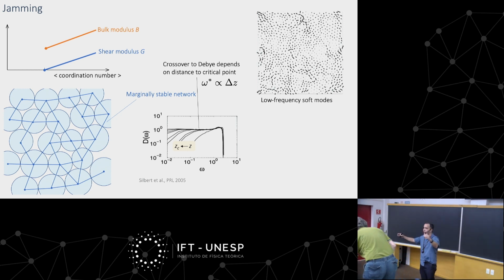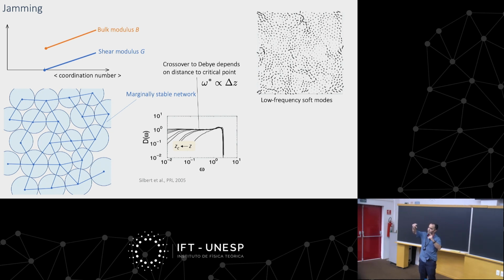an elastic material in terms of an elastic free energy. For this example of the disks, you apply some compression, and you have some energy cost associated with the compression. The energy term associated with the compression is proportional to the bulk modulus. I'm sorry, I just have these disks that don't interact. They just either touch or don't touch. Yes. If you keep compressing, they can rearrange. So there is an effective interaction.